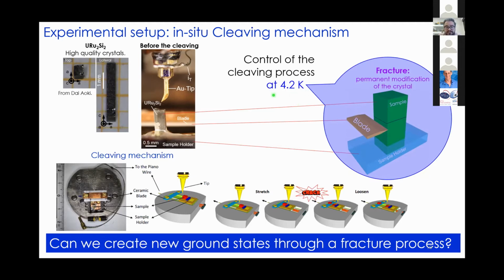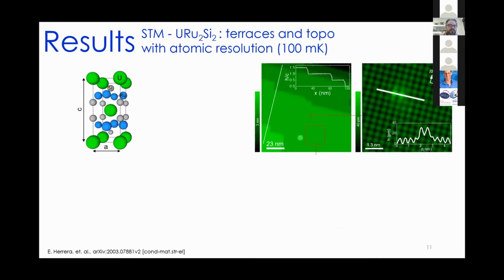And after cleaving the samples at these temperatures, we got this kind of beautiful images that, as you can see here in this profile, we have square terraces, and the distance between consecutive terraces is always proportional to a half of the unit cell in the z-axis direction. In these terraces, we have atomic resolution, and the interatomic distance of the square lattice that you observe in this image corresponds to the distance that we have between uranium atoms.